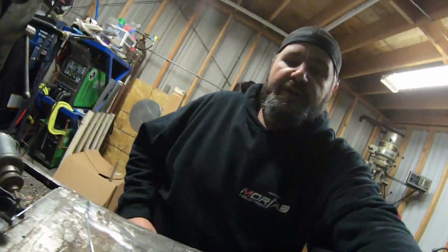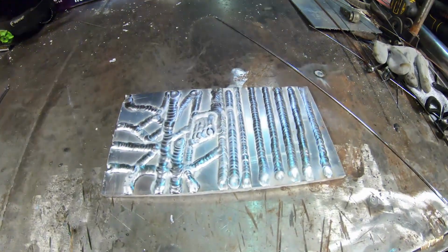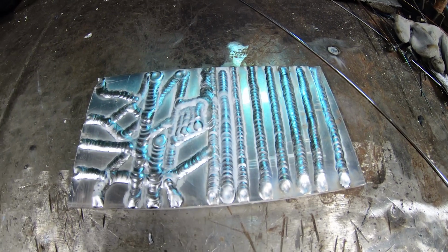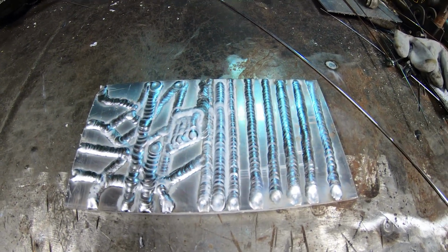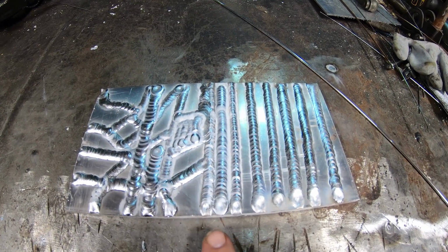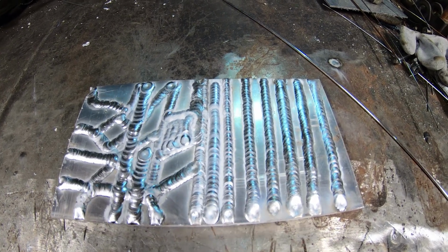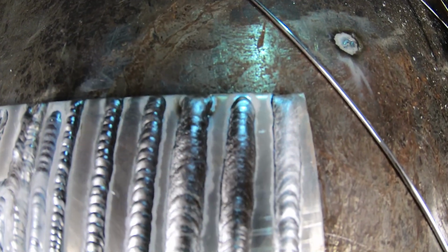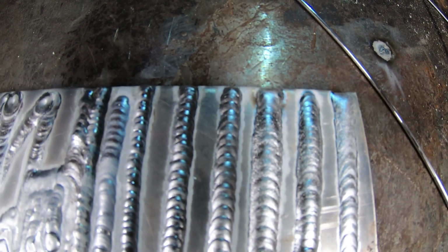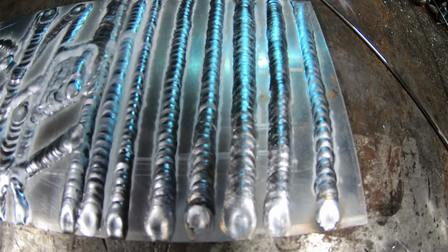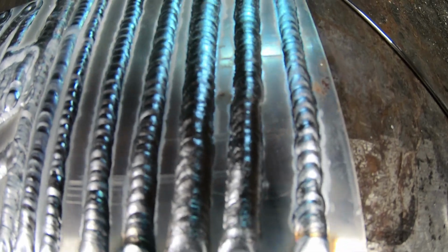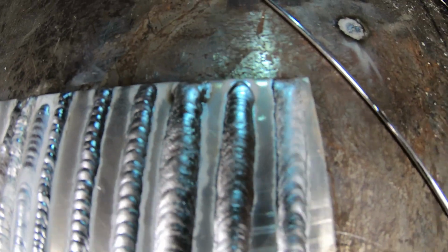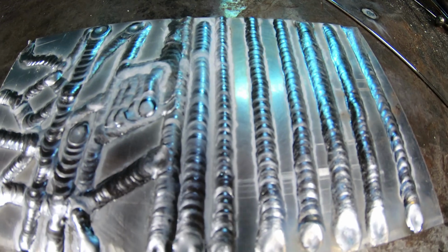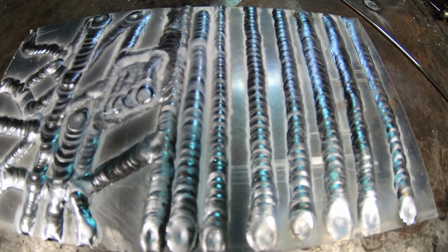But there was one interesting thing that I wanted to show you guys about aluminum and why you have to be careful with it when you're welding it. I didn't let this plate cool at all in between any of these welds. You guys saw it was straight up welding. You can see these beginning beads look pretty decent. And then towards the end, you start to get this weird issue where you don't see ripples anymore. You start seeing the dimes, and then all of a sudden they just disappear. Well, that happens a lot when you don't let aluminum cool in between weld sessions.